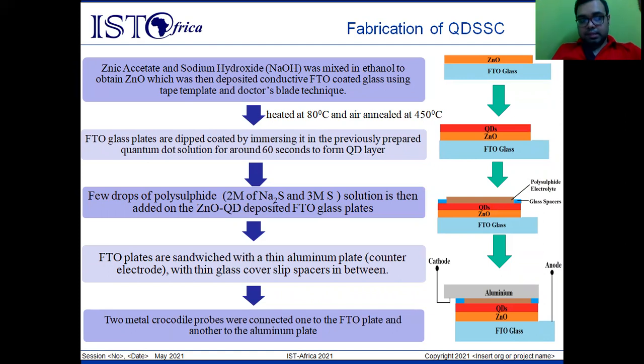Then we dip coat, that is, we just dip the oxide deposited FTO glass plate in the previously prepared quantum dot solution to form a quantum dot layer on the oxide. And finally, we add a few drops of polysulfide electrolyte, add two glass spacers, so as to prevent any kind of short between the photoanode and the counter electrode. And finally, we sandwich it with the aluminum plate to form the solar cell. As you can see, we connect the cathode and anode terminals by using normal crocodile probes and test it under illuminated white light condition by a xenon lamp.